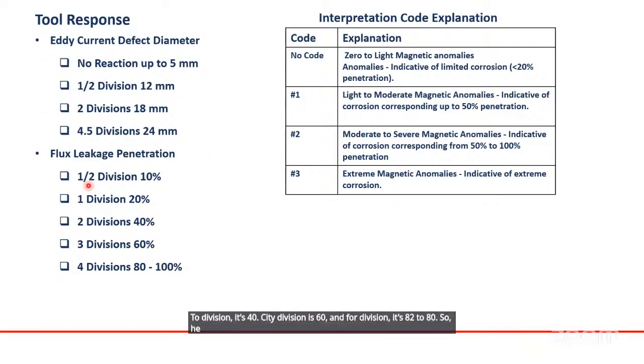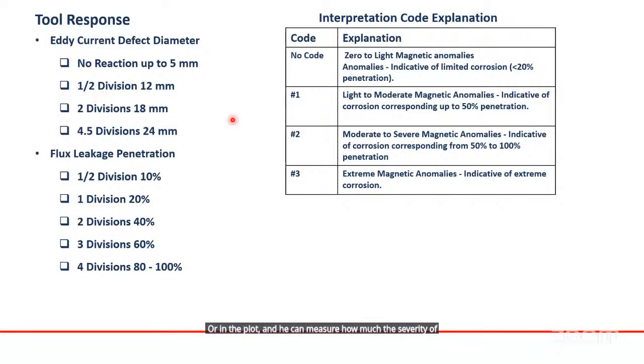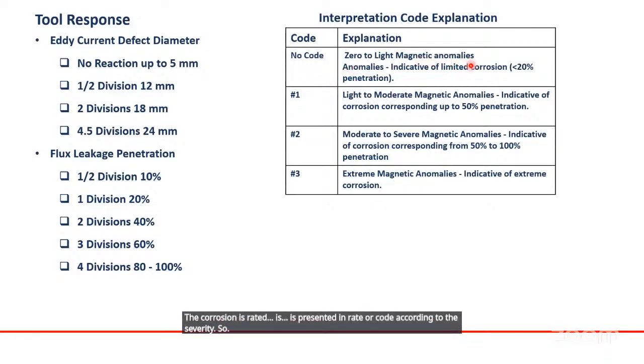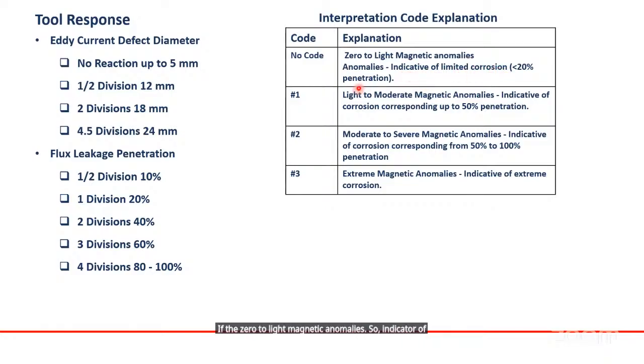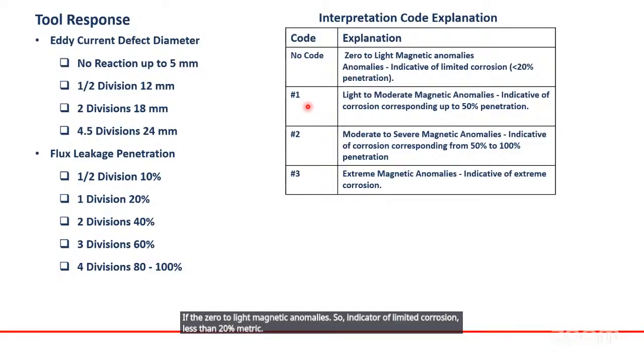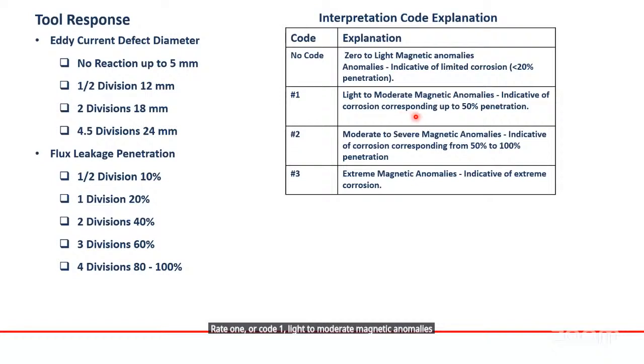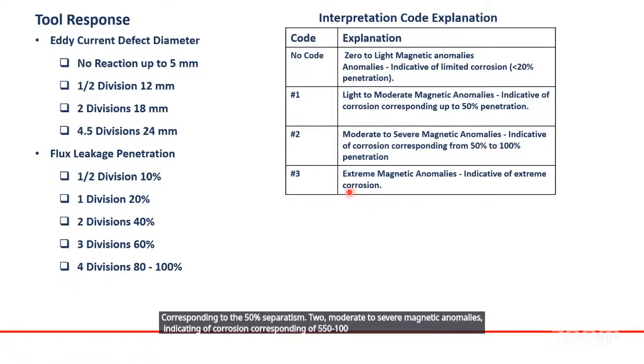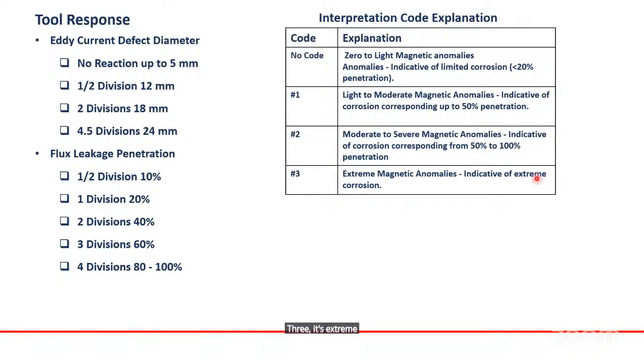So he measures this and scales it on the log or plot, and can determine the severity of the corrosion. If it is less than 20%, it is rated 0, or there is no rating. The corrosion is presented as a rate or code according to severity. Rate 0 is light magnetic anomalies, an indicator of limited corrosion, less than 20% penetration. Rate 1, or code 1, is light to moderate magnetic anomalies indicating corrosion corresponding to up to 50% penetration. Rate 2 is moderate to severe magnetic anomalies indicating corrosion corresponding to 50 to 100% penetration. Rate 3 is extreme magnetic anomalies, indicating extreme corrosion.